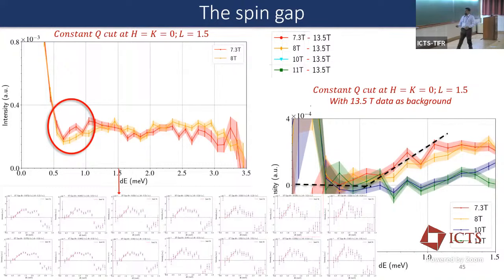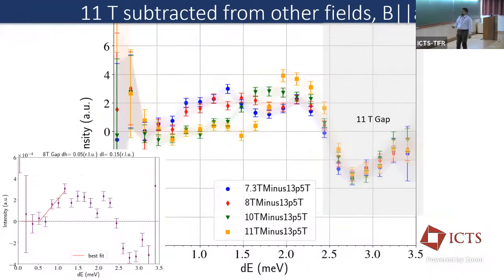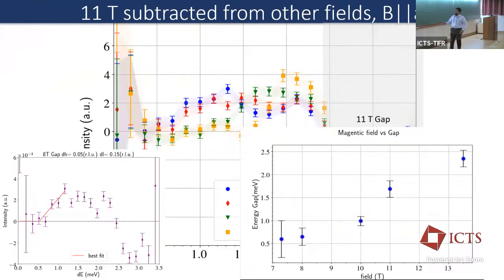We have gone through a huge amount of analysis to figure out what kind of cuts we should make, how broad our cuts should be, and a whole error analysis on top of that, which I can go into detail if you're interested. We also subtracted the 11 Tesla data to see what if we use that as a background. One of the plots that we have right now is the gap versus field, and it looks like this. So at 7.3 Tesla it's kind of iffy, but from 8 Tesla onwards it seems that it's gapped and it rises as a function of field.